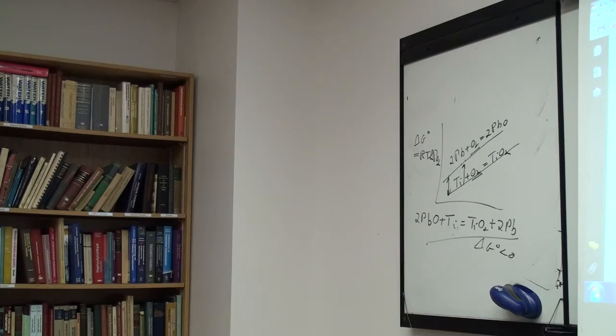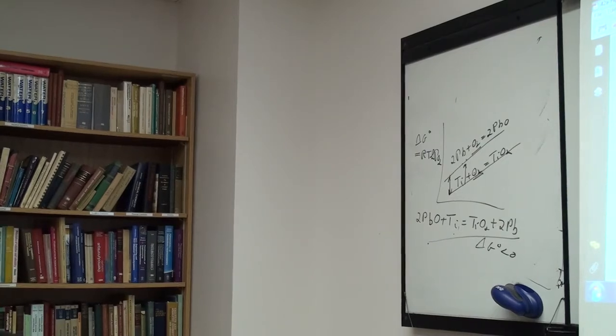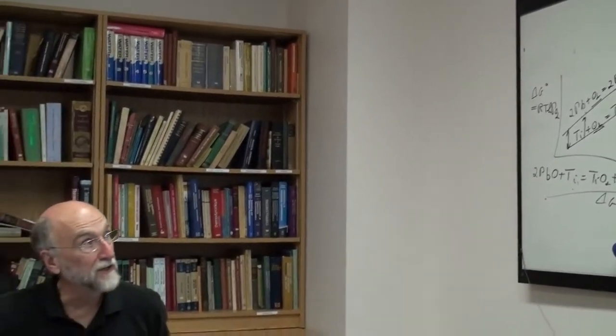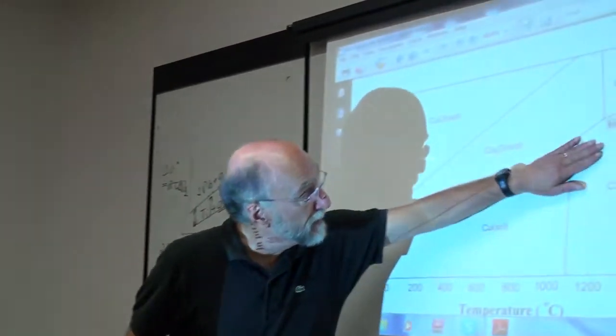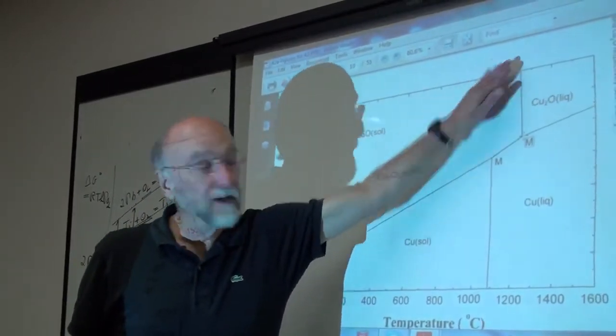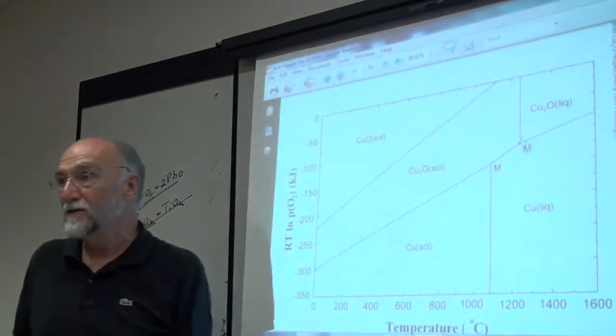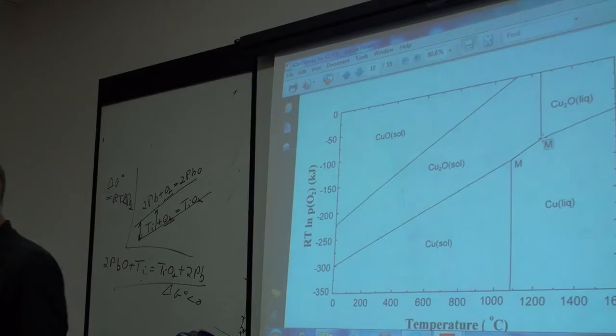On these diagrams, you often have a little M to indicate the melting point on this line. You don't draw this line. You would just have this line, you'd see a kink here, and you'd see another kink here, and you'd see an M here, and here you see a little M in a box to tell you that that's the melting point of the metal, and that's the melting point of the oxide. Okay, so the diagram for copper and Cu2O would be this line, but you wouldn't have this little vertical line. If I draw in the vertical lines, now I've got a phase diagram.